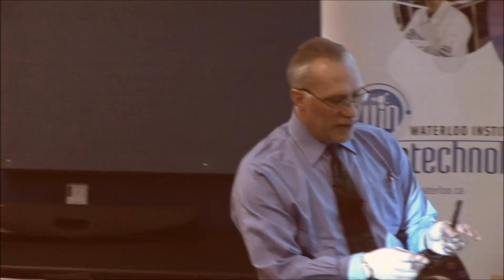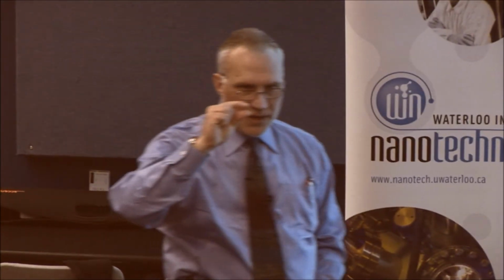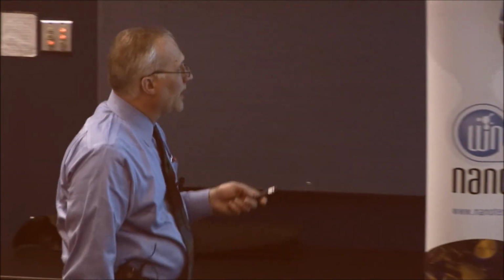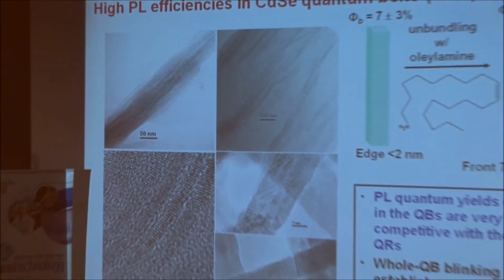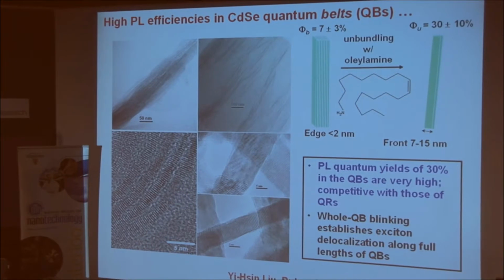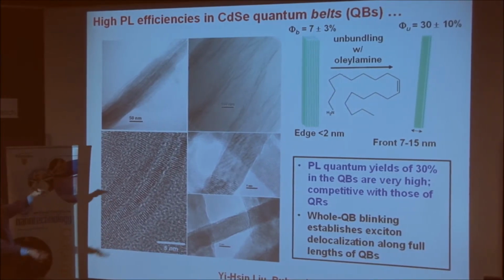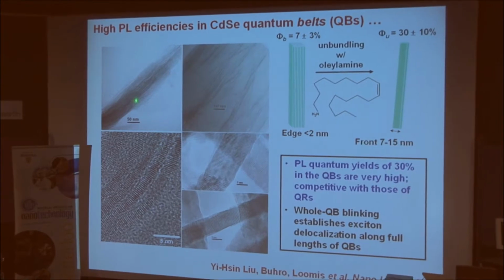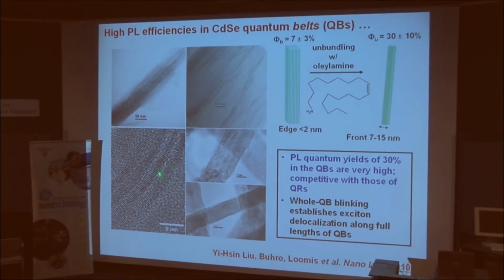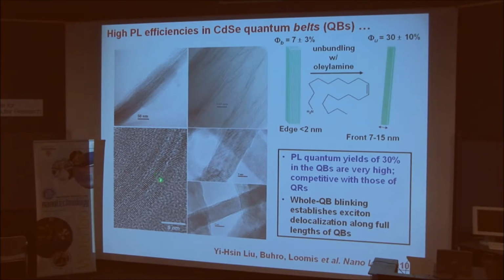Instead, it always gives belts that have a significant width, a fairly long length, and a very thin thickness. And so what you see here is how the belts are first obtained from the synthesis. This is actually a bundle or a stack where the belts are stacked up face to face to face. And if you look at that bundle at higher resolution, you can actually measure the thicknesses of the belts. So here's one belt, here's another belt, here's another belt. These are all stacked one upon the other. And the thickness of these belts is 1.8 nanometers.